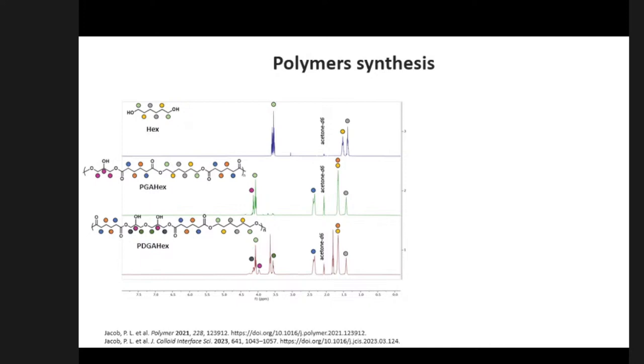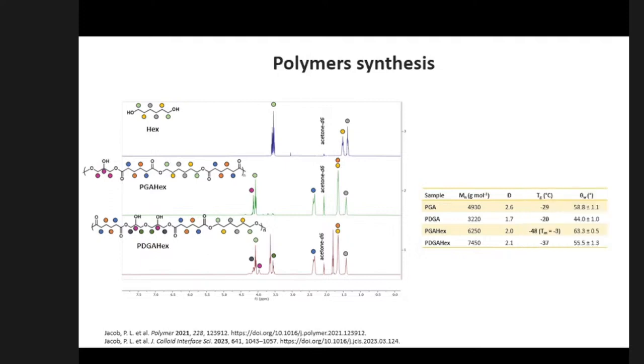GPC analysis was performed to evaluate the successful polymerization, and as you can see from the table, PDGA showed a lower molecular weight compared to PGA because of the diglycerol lower solubility in water, whereas hexanediol-based polymers showed higher molecular weights because of hexanediol higher solubility in THF. All the synthesized polymers were amorphous with glass transition temperatures below minus 20 degrees, and their wettability was evaluated by contact angle measurements. PDGA showed the lower contact angle compared to PGA because of its higher hydrophilicity, and the same trend was found for hexanediol-based polymers.